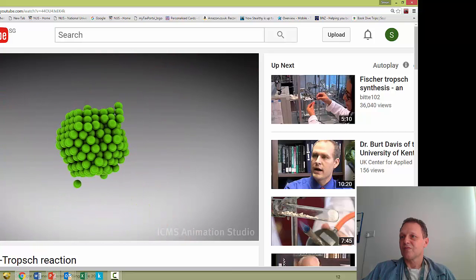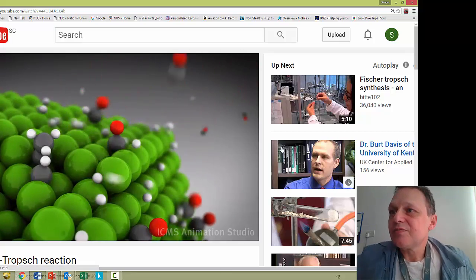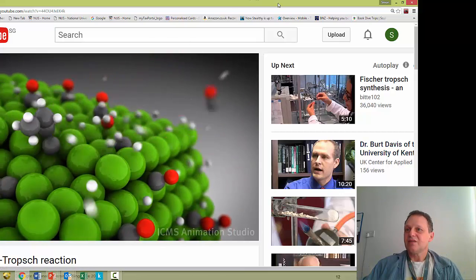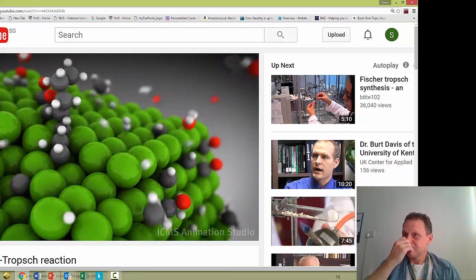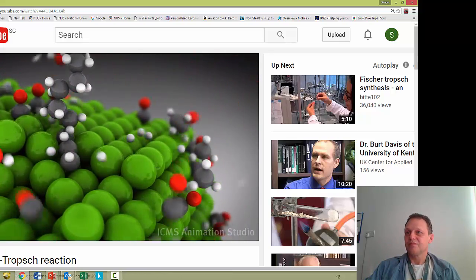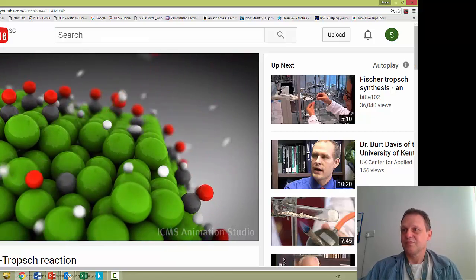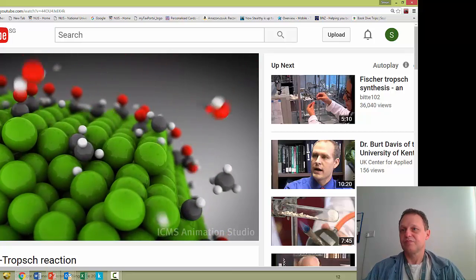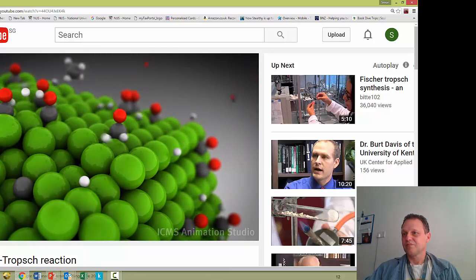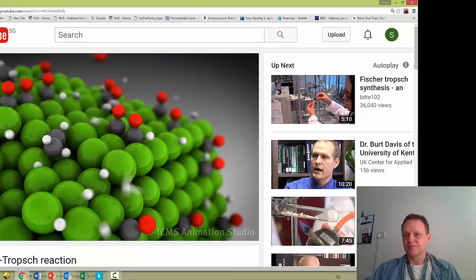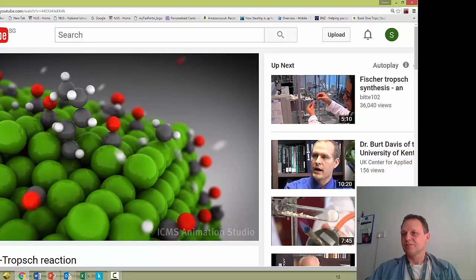Only on particles that are large enough to support an open corner with coordinatively unsaturated ruthenium atoms can the formation of hydrocarbons occur. On the highly reactive ruthenium atoms in this open corner, carbon monoxide rapidly decomposes and generates enough free carbon to sustain a chain growth mechanism. To allow this process to continue, it is necessary for newly formed carbon-hydrogen moieties to move away from the dissociation site. This mechanism of rapid carbon monoxide dissociation and carbon relocation was discovered in quantum mechanical calculations.